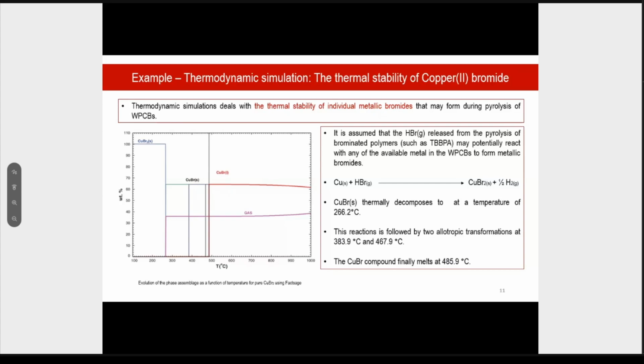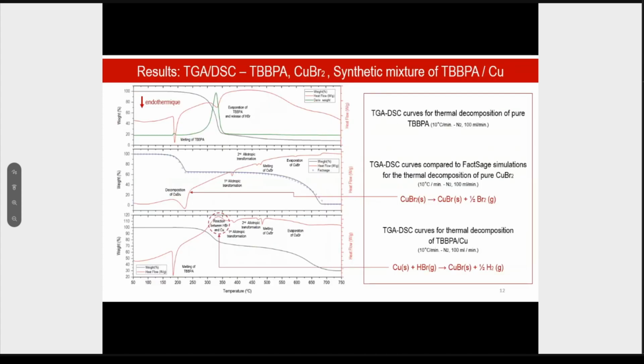As you can see, in the simulation of copper 2 bromide, 1 gram is introduced to the system at 25 degrees and 1 atmosphere. The system is then heated to 1000 degrees. According to this calculation, we can see that copper 2 bromide is firstly decomposed to copper 1 bromide. This is followed by two different allotropic transformations. Then copper bromide starts to melt and then evaporate. So this was done using FactSage.